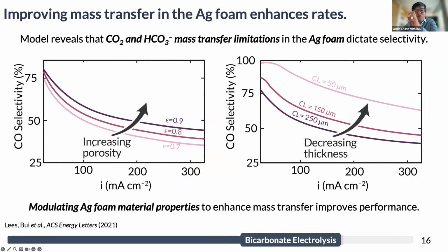So we find that if you can control and improve that mass transfer, for instance, by increasing the porosity of the silver or decreasing the thickness of that foam, you can dramatically improve the selectivity of CO to your value-added product. And so ultimately, this led us to really understand that when we want to improve these bicarbonate electrolyzers, modulating the properties of these silver foams is going to be really important to improve performance by tailoring the mass transfer of this bicarbonate delivery and the CO production within that complex porous electrode.